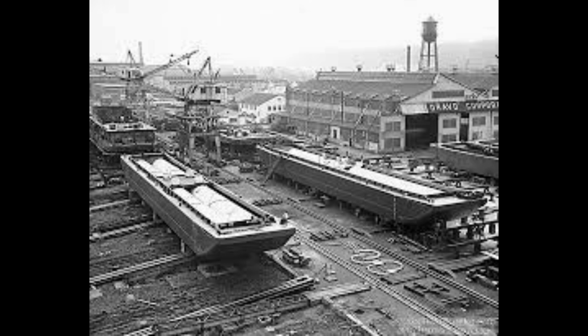Their experience with pressure vessel construction had taught them that stress relieving through controlled heating and cooling after welding could eliminate residual stresses. But you can't heat treat an entire ship hull. Instead, CB&I developed localized stress relief techniques, heating specific high-stress zones with special torch arrays, allowing controlled expansion and contraction, then cooling slowly. This process added days to construction time, but it prevented catastrophic failures months later when ships encountered extreme conditions. By early 1944, every LST coming off the production lines underwent stress relief treatment on critical welds before being